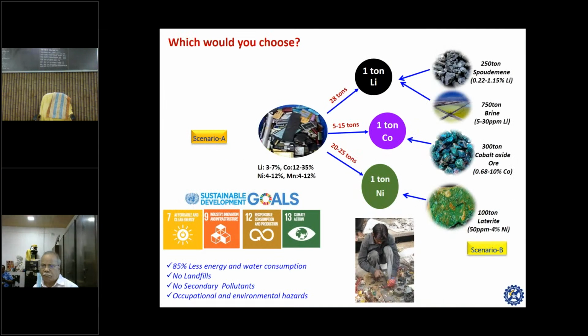On that pretext, we would ask you, what would you choose? Scenario 1, where you get lithium as 3 to 7% in the batteries: from 28 tons of these batteries, you can make 1 ton of lithium. Or you would need 250 tons of spodumene to get 1 ton of lithium, or 750 tons of brine to make 1 ton of lithium. So there is a 10 to 30 times escalation in the raw material factor, which governs a lot in the economics of the process, and its availability is a bigger concern.